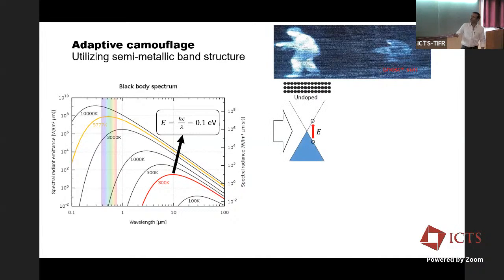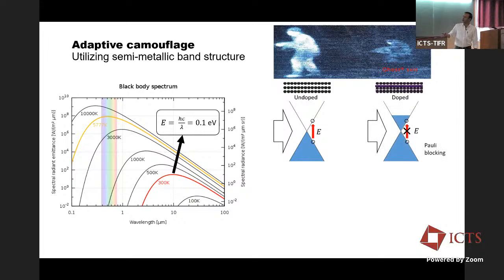So imagine you have a graphene, which has a conical band structure like this. If I do not dope at all, then lights of this energy can come and the electrons can be absorbed and graphene will re-emit and you can see the cloth. Now, if I dope it and there is no state available because these states are already occupied, the transition cannot take place, which means that the light cannot be absorbed or re-emitted. As a result, by having a cloth which is like a doped graphene, you can stop the infrared radiation from being absorbed or re-emitted.